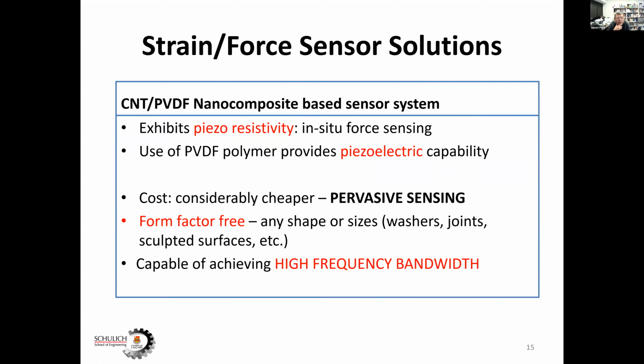So we thought, can we make a sensor that we can spray paint onto different surfaces, okay? And we use what's known as piezoresistive and piezoelectric capabilities. And we are using both of these through sensor fusion, okay? Piezoresistive provides low frequency, and piezoelectric provides high frequency. So by combining these two, we can measure both high as well as low frequency. And because of the spray paint, we can apply these things to any surface.